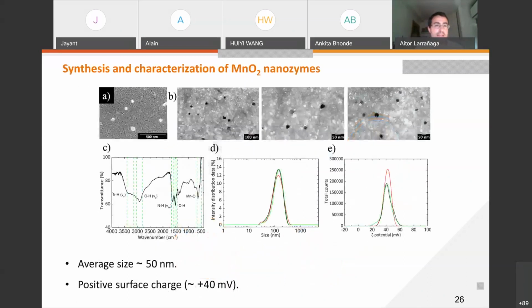So first of all, we synthesized and characterized these manganese dioxide nanozymes. This synthetic procedure was performed by Dr. Christos Tapeinos and Professor Gianni Ciofani at the Italian Institute of Technology. As you can see in these scanning electron and transmission electron micrographs, these nanozymes were more or less round-shaped with a diameter around 50 nanometers. And they have a strong positive charge because of the use of polyallylamine hydrochloride during the synthesis procedure.